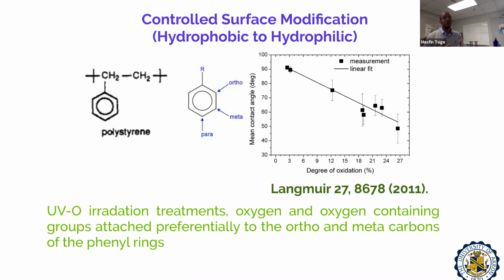And this obviously benefits us with the earlier fundamental question I talked about. Can I continuously control the confining surface properties? And this pretty much gives us that option. The one challenge they had in their case was the large error bar in their data. That was very hard to avoid because you have a much larger surface, usually in the order of centimeters, and they are exposing that to UV radiation. So there could be different variation in the oxygen distribution on the surface.